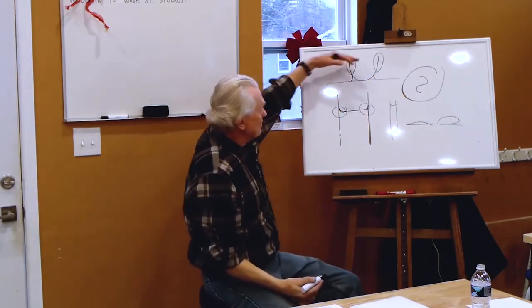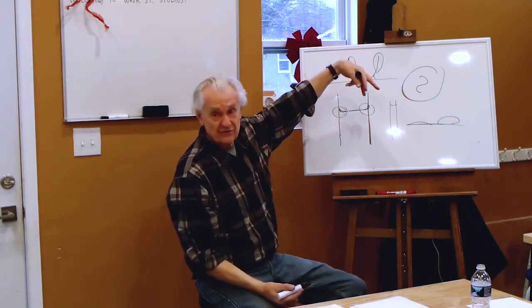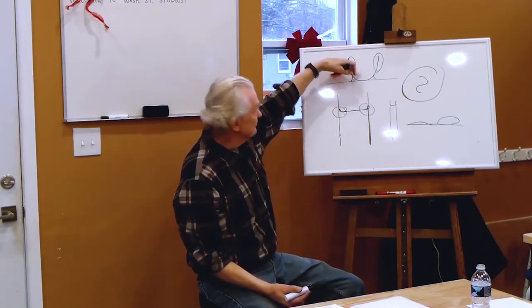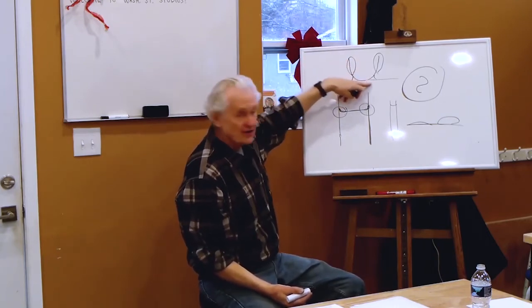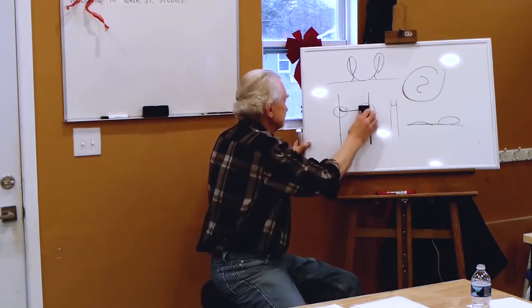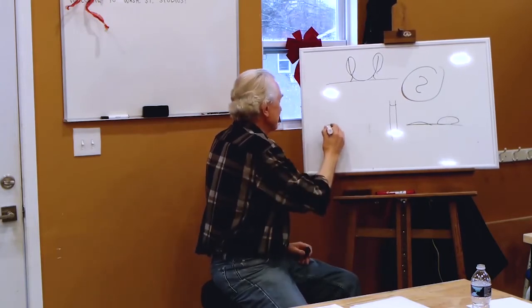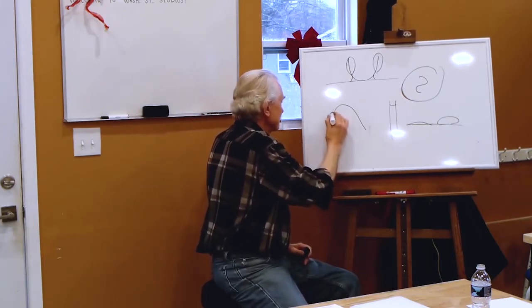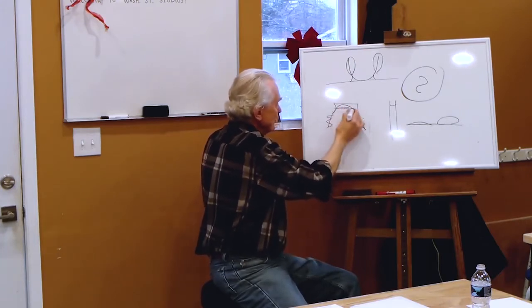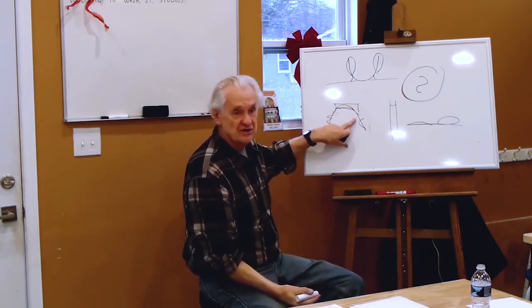I'm normally waiting for it to dry a little bit so that I can turn it over and trim it. I'm waiting for it to stiffen up. So this part's getting dry. This part down here is not doing a lot of drying, because it's thicker and it's stuck down close to the bat. Now I turn it over and go to trim it. I've got it upside down now, and I've got this extra clay here. This part has already dried, and I trim this, and now this part wants to shrink. Well, it can't shrink much because this part is already rigid.